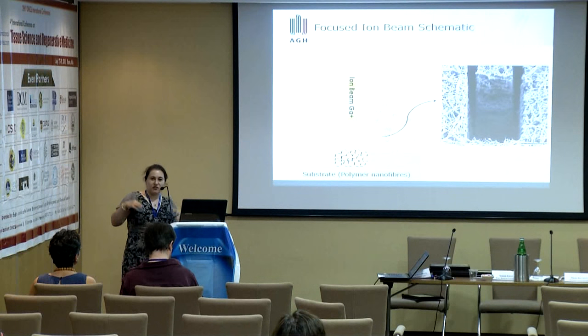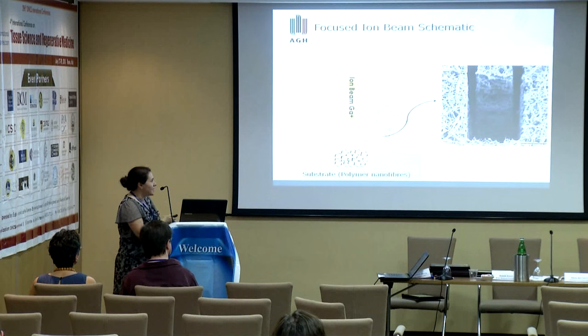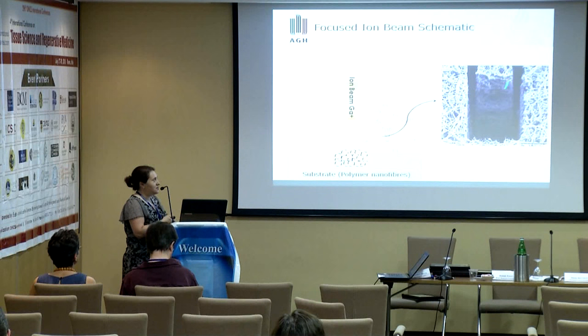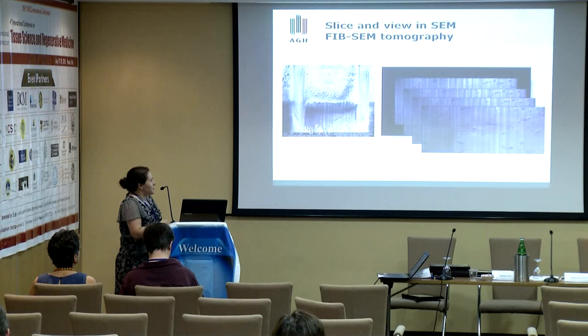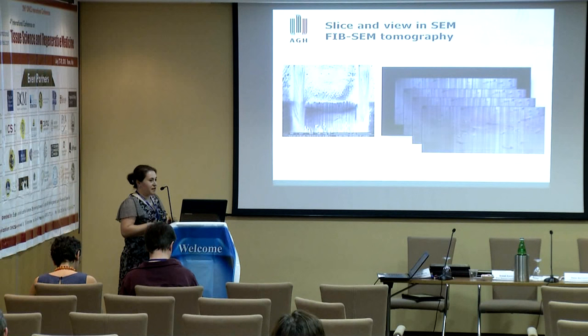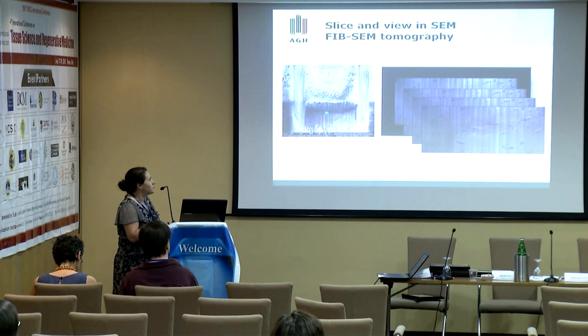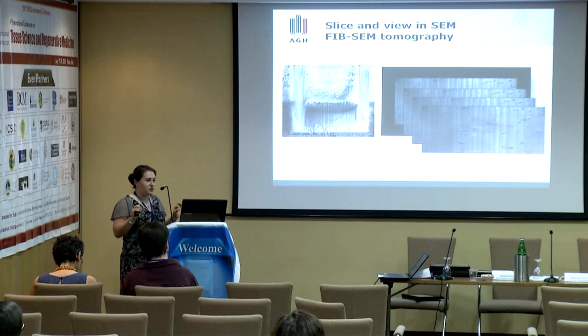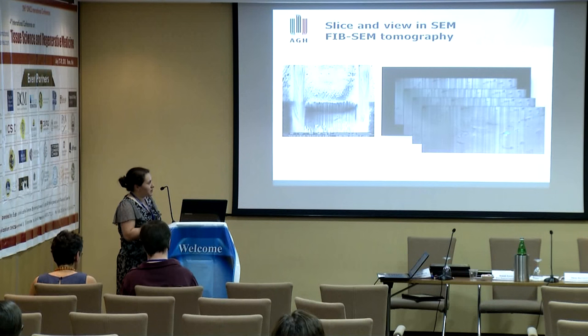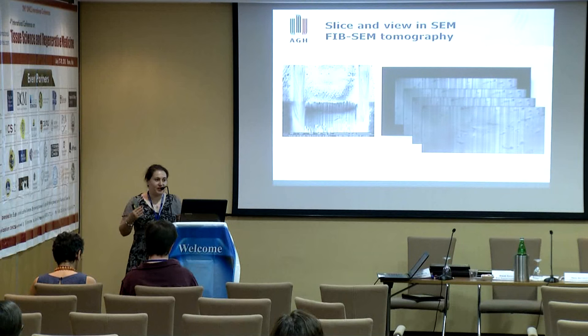We can see how the whole structure of nanofibers looks inside. We can also do this in a cryo environment. This is an example of nanofibers frozen with water where we do slicing. On the cross-section you see dark spots which are cross-sections of the fibers that we can use for the whole reconstruction.